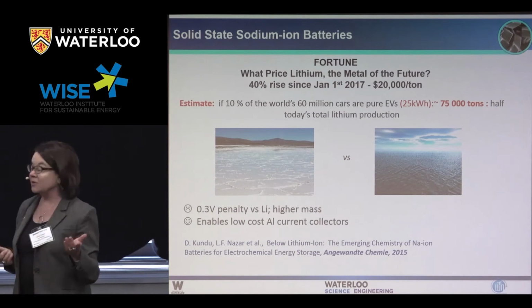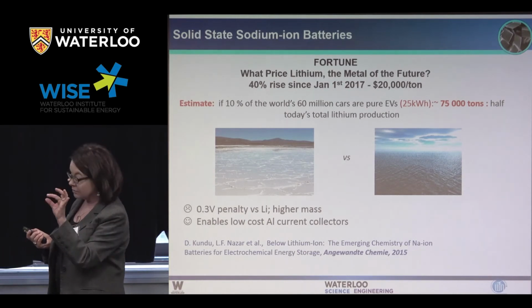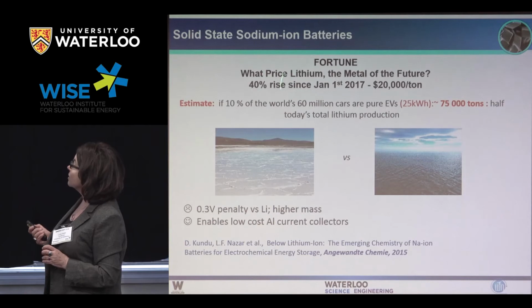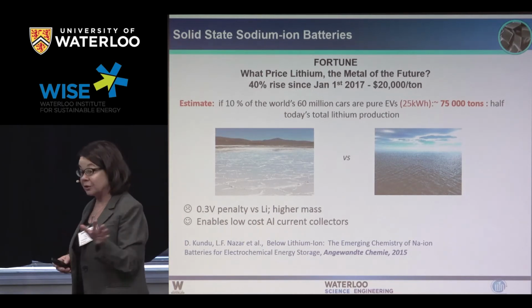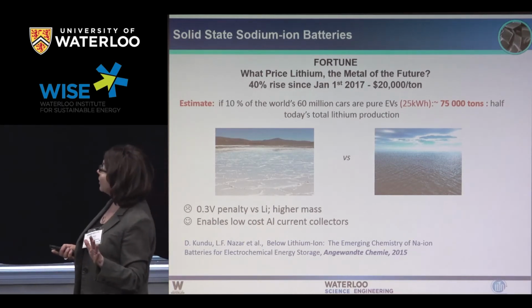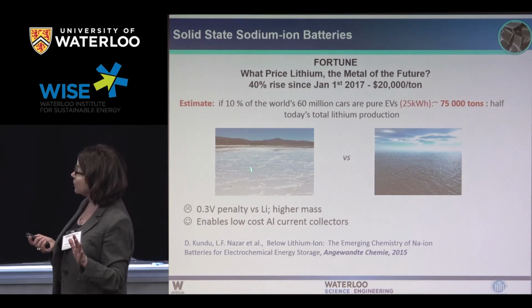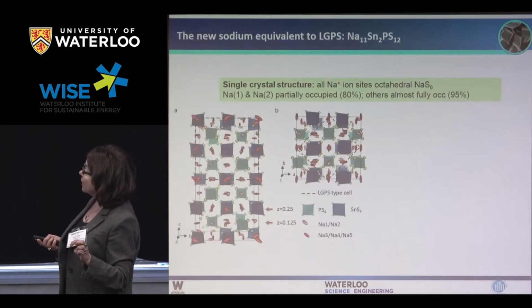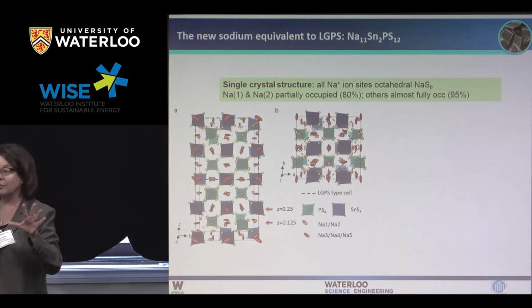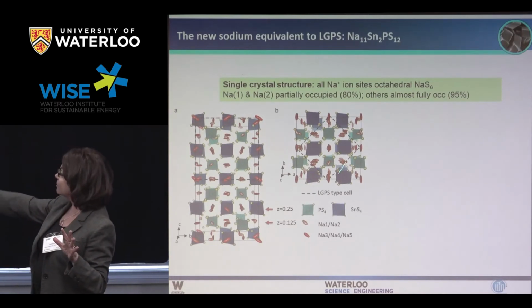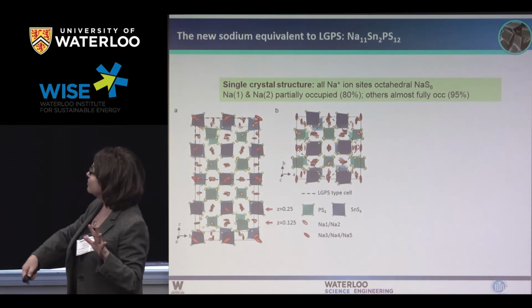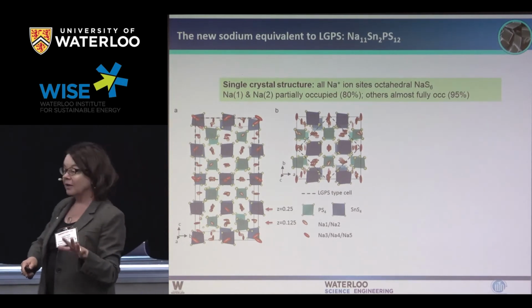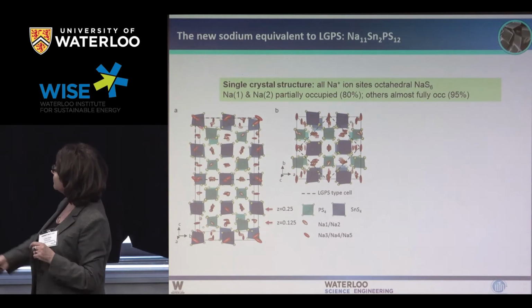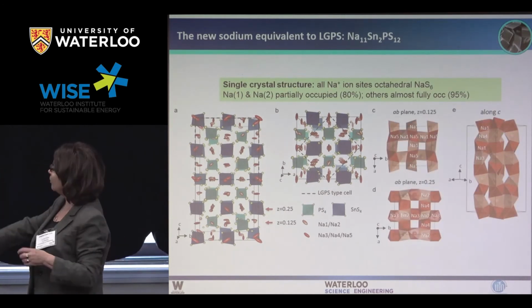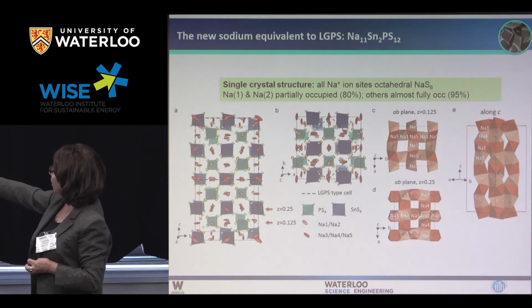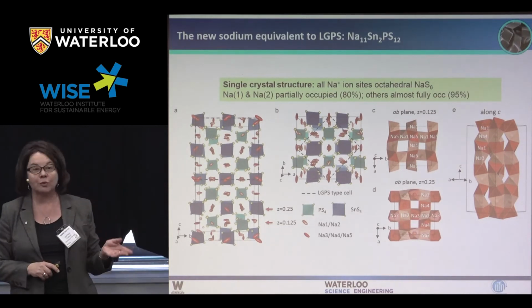So sodium has almost the same potential as lithium. It's just a little bit of a penalty, and there's all sorts of advantages. It's a little bit heavier, but especially for grid storage, it has a lot of possibilities, and obviously it's abundant, whereas lithium is not. So again, I apologize, this is a crystal structure, but the point here is that here's our parking lot. We have a nice framework structure, and it's built of tin and phosphorus and sulfur, and those are nice low-cost elements. And superimposed upon this framework structure, we have effectively the little parking lots, or you can call them conference rooms.